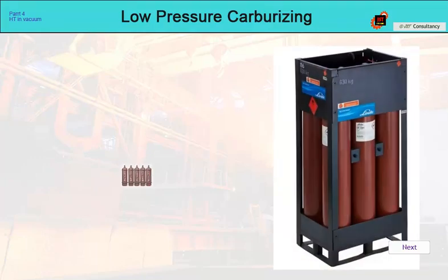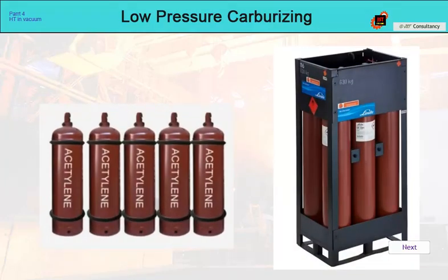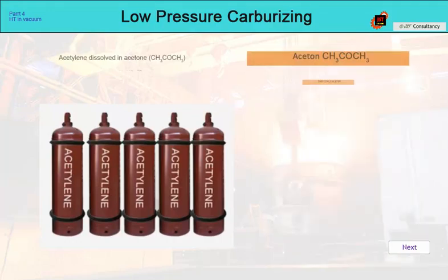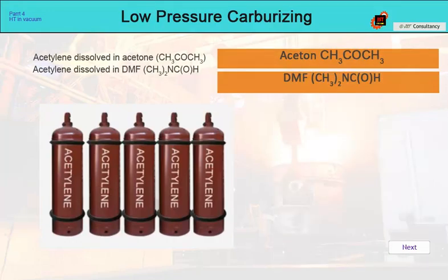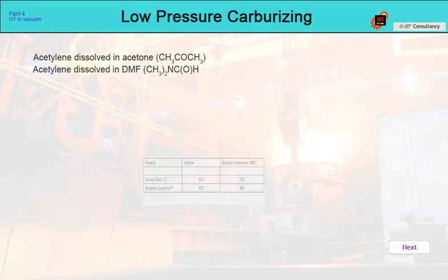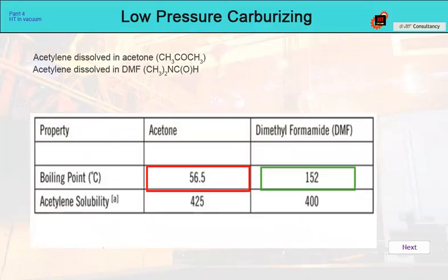For carburizing under reduced pressure, it is also necessary to consider the type of acetylene. It can dissolve in both acetone and DMF, which is dimethylformamide. Acetone, like DMF, contains oxygen in its molecule. This can negatively affect the carburizing process. Therefore, its presence in the low-pressure process is undesirable for the stability of the carburizing. However, since DMF has a boiling point 100 degrees Celsius higher than acetone, this acetylene solvent will most likely not enter the working chamber, and the process will be more stable and safer.